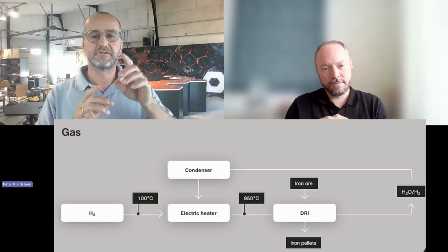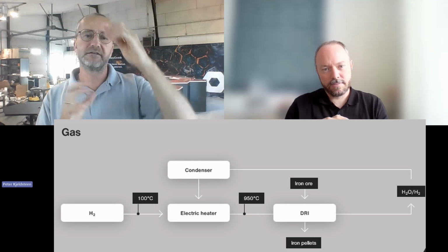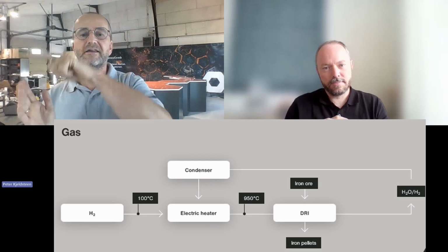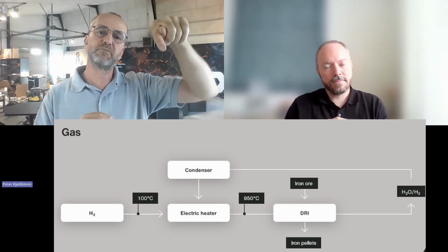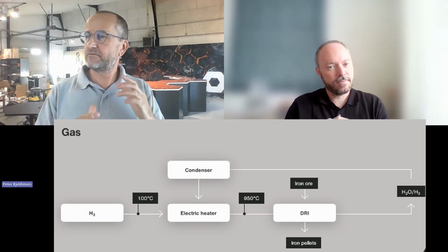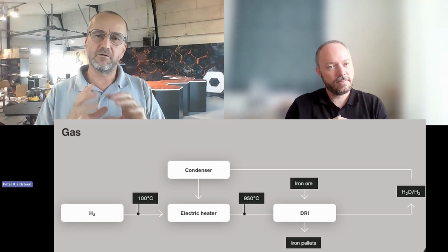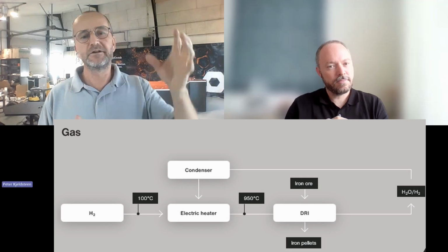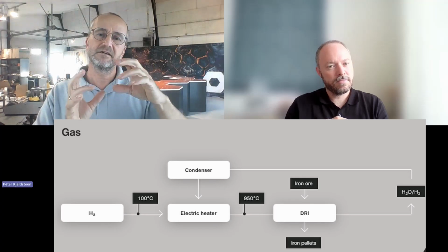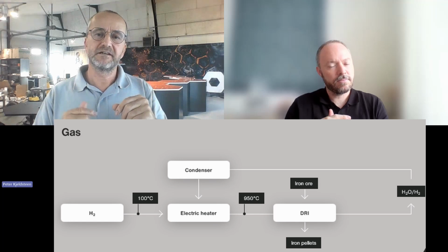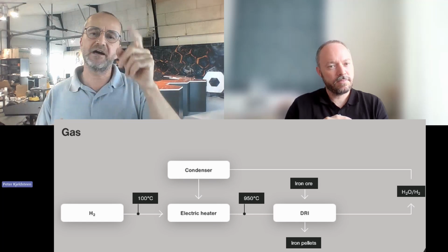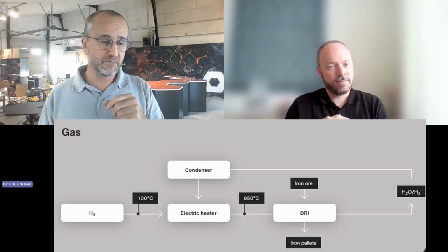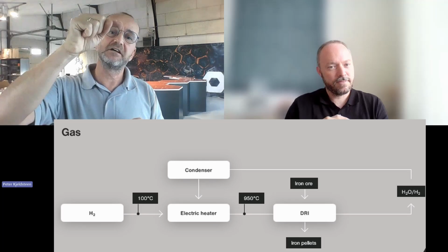Then when the hydrogen has passed over, it is turned into water and iron, but there's still hydrogen remaining. So you'll make a loop and take the outlet gas from that process back into a condenser, remove the water, and bring in the remaining hydrogen. But very often in your iron ore, there are also some residues of carbon. And when you put hydrogen into that system, you have lack of oxygen. And the gas coming out is typically carbon monoxide. And carbon monoxide coming back, it is not condensed out. It will go back into the system.